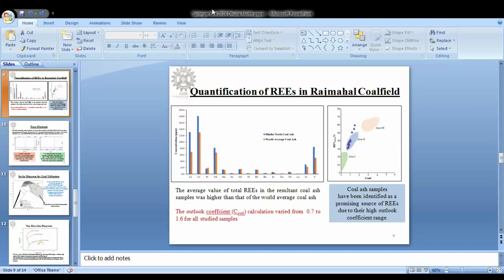So in this case, what we saw was that most of the depths had the calculated outlook coefficient from 0.7 to 1.6 for all the samples which we studied, and hence we concluded that these coal ash samples are a promising source of rare earth elements, and it is definitely worthy to pursue in terms of exploration or extraction of rare earth elements, which is anyway the next step after the exploration studies.